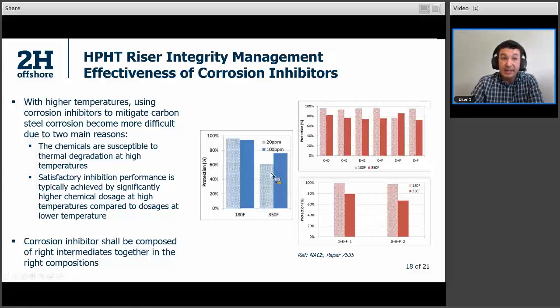And the second one is that high temperature may affect your corrosion inhibitor integrity. So you may lose the chemical's integrity in the corrosion inhibitor, and that may block the injection system. And if you are trying to use a corrosion inhibitor in high temperature conditions, you need to use higher chemical dosages compared to the lower temperature conditions.